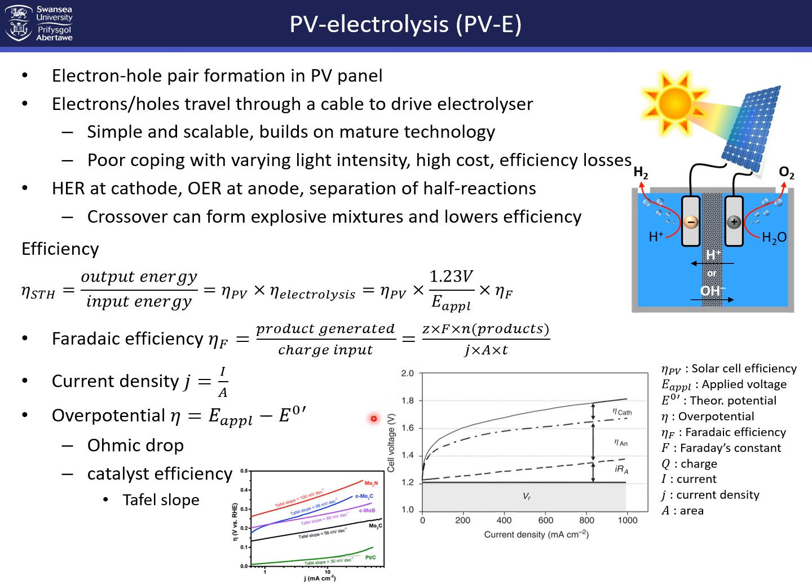The voltage depends largely on the overpotential and the ohmic drop. I've talked about this in the lecture a little bit. If you have a large resistance across the membrane, you have to apply an extra voltage just to make those counter ions diffuse through the cell. And the larger your current density, the higher the ohmic drop. So if you increase the current density, your ohmic drop increases and you have to apply more and more voltage and your efficiency goes down.